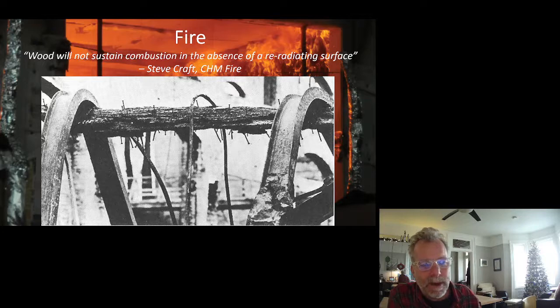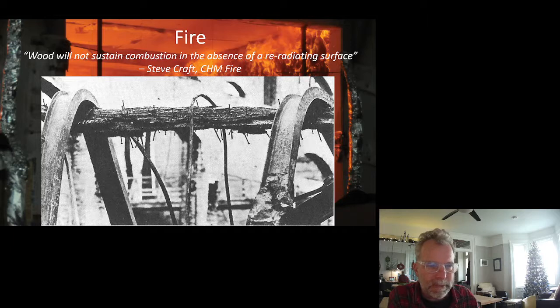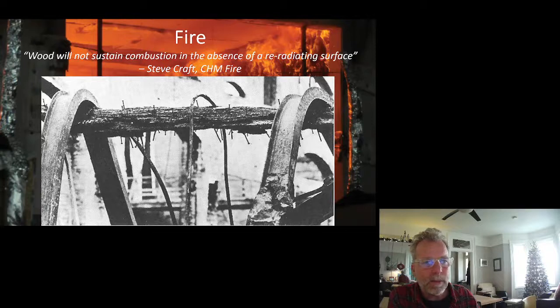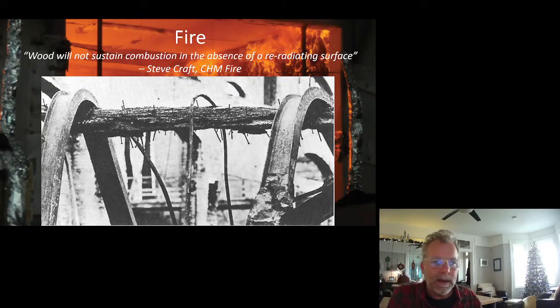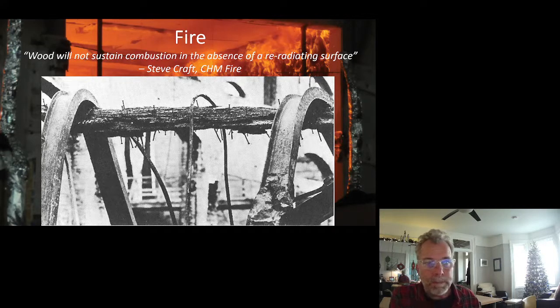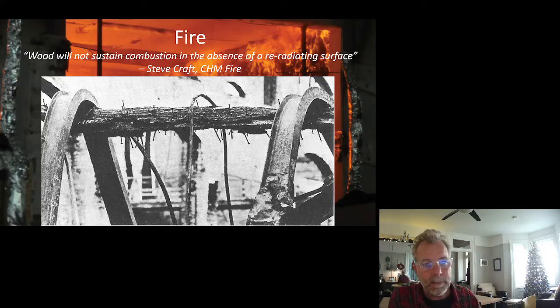This image is from the San Francisco fire of 1906. This is an example of a post-fire building that had collapsed — we can see the steel beams during the fire heated up to a point where they lost their stiffness and ended up drooping and sagging. The wood beam preserved its form. You can see that it charred from the outside, but it preserved its form.